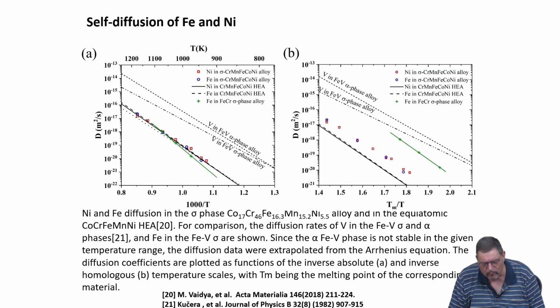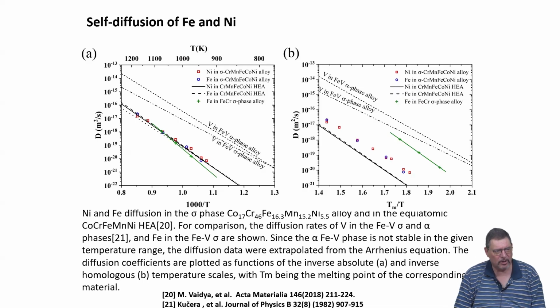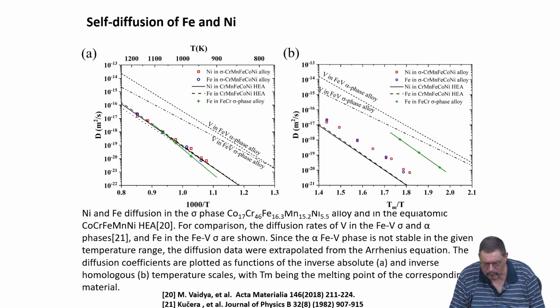You see, depending on how you plot, a little bit of a difference between the measurements in the high entropy system and the measurements in chemically much simpler systems. But again, I mean, here the difference is a little bit larger, right? So you could say here that you have an indication of some sluggishness of the diffusion process.